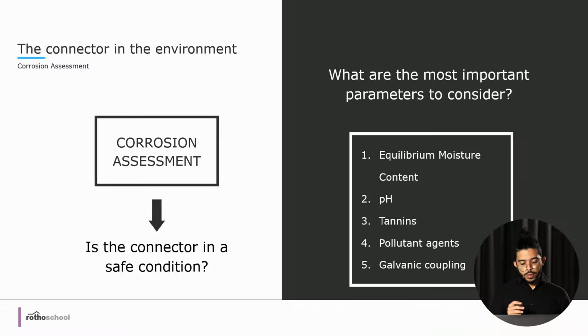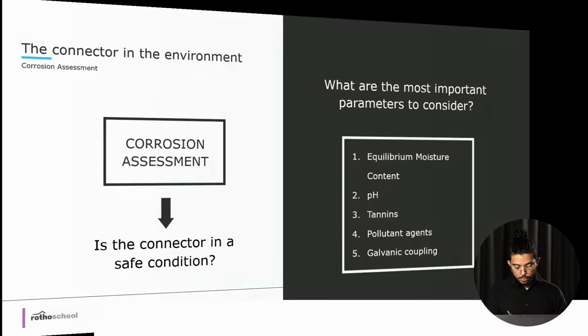For this assessment, the most important parameters to consider are right here. We saw how the equilibrium moisture content affects the aggressiveness of the classes, whether it is the atmosphere or the timber. We also checked how the pH, the acidity of the timber, affects the corrosion. Point 4, polluting agents, chlorides, mostly determine the atmospheric corrosion class, and we saw that too. So we are left with two important points: tannins and galvanic coupling. Let's take a look at the first, tannins.